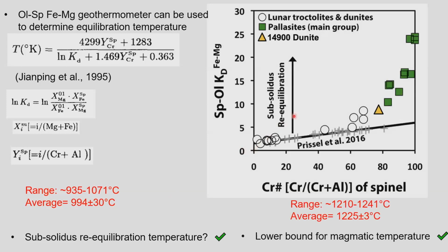So plugging in these very detailed chemical information from the olivine in the clast and from the chromite grains in the clast, which we needed both minerals to do that, what we found was that this dunite clast, which is this point right here, is off of what's called an equilibration line. So what that means is if I form this dunite and I form the olivine and the chromite, and they were in equilibrium, which means they formed at the same time, the chemical composition of that chromite compared to that of the olivine would have to follow this line.